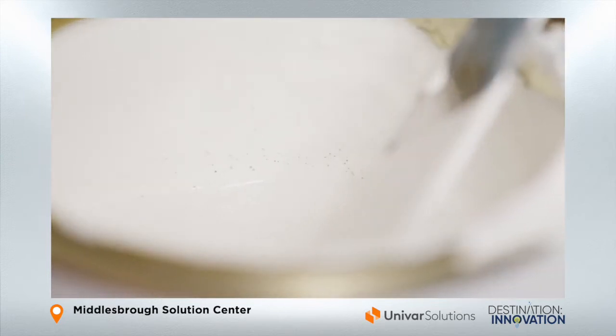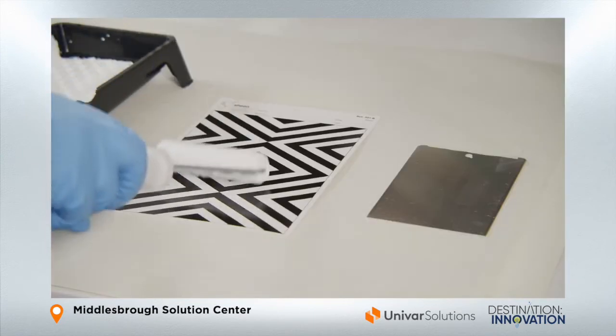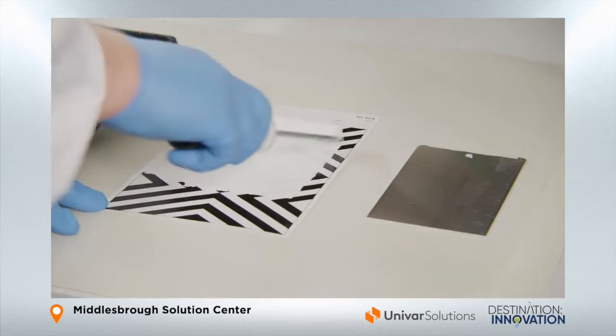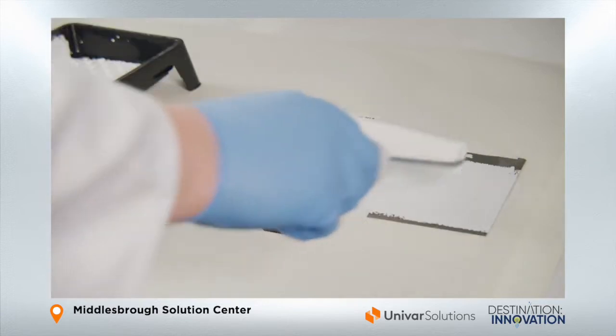Yeah, definitely. You can see here the first one is an example of a paint with the defoamer added, where you can see there's not really much foam at all. Whereas the second one is a paint without defoamer, and you can see in the paint itself there are already some little bubbles there. So during the application process, which is obviously a relatively forceful process, even with the more basic type of rollers, you do see lots of little pinholes which will cause a problem.